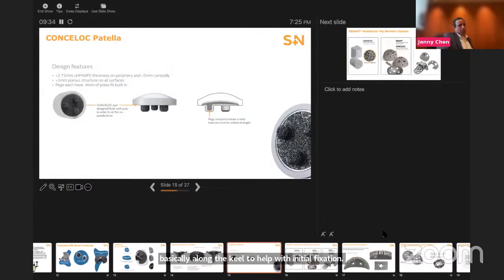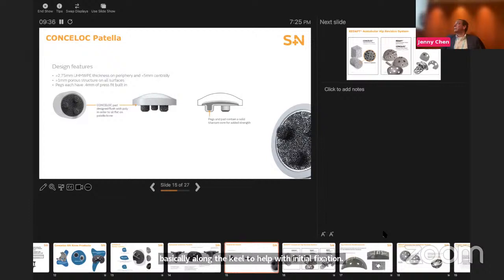And this is our patella. We basically 3D print the patella. We do print a solid substructure, because 3D printed material that was completely Concelloc structure was not strong enough in the peg shear during testing. So we had to go back, basically underneath this surface, it's solid, and then Concelloc structure on top. Then we go in and we compression mold the polyethylene on top, round and oval.